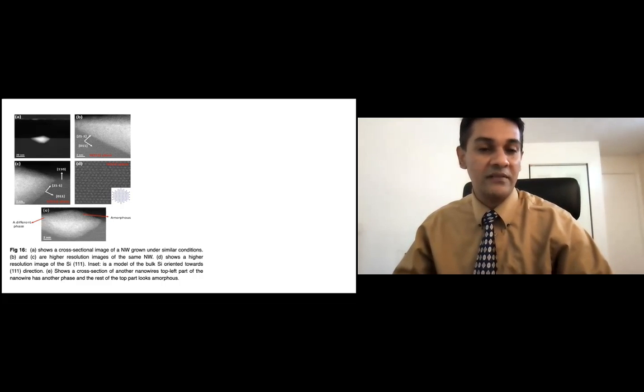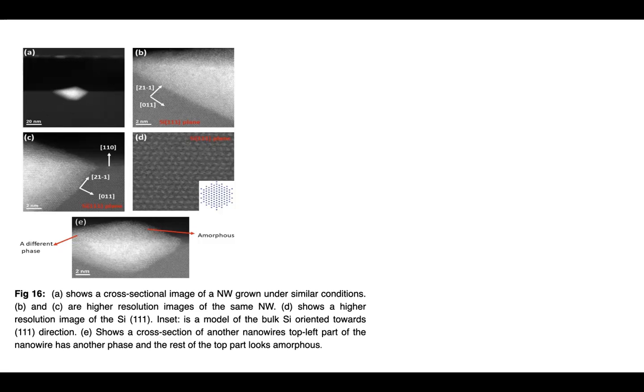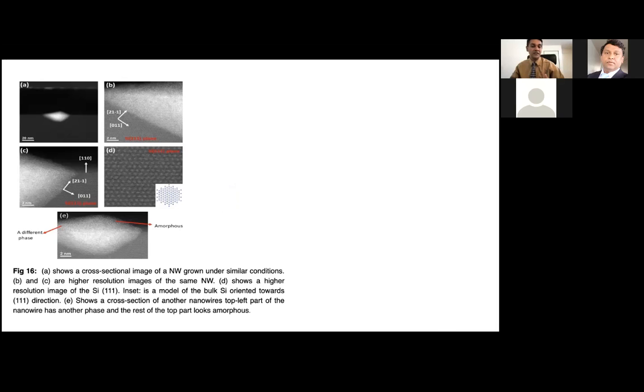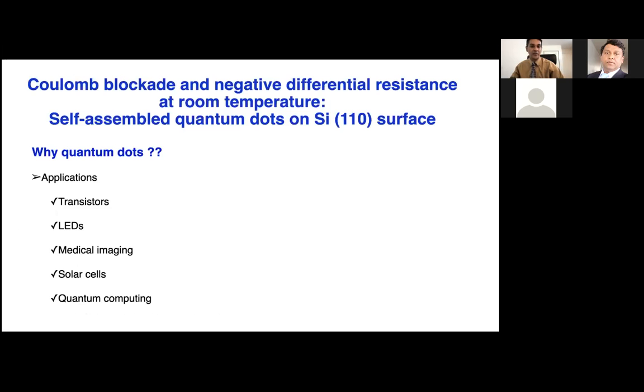Then, close to the bulk silicon, we identified some ordered structure of the nanowire. So we wanted to see what kind of iridium and silicon combination it is, and we measured the interplane distances between the atoms. We found that this combination is iridium disilicide. There are different phases of iridium silicide: IrSi, IrSi2, IrSi3. Among these, we found that this ordered structure close to the bulk silicon is formed from iridium disilicide, which is a semiconductor. It shows semiconductor properties.